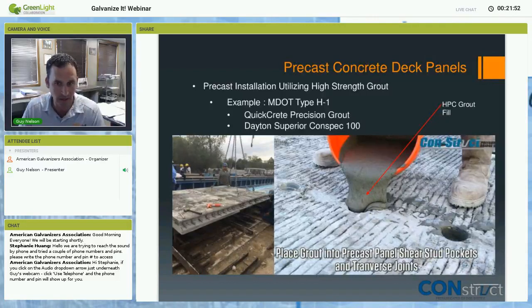What we do is we have shear pockets that then accept the shear studs, and once the deck panels are placed on the tub girder, we fill those pockets and the joints between the individual precast panels with a non-shrink high strength grout. For this particular project, we used an MDOT type H1 because it was an MDOT project, and most states have pre-qualified grout, high strength grout systems.